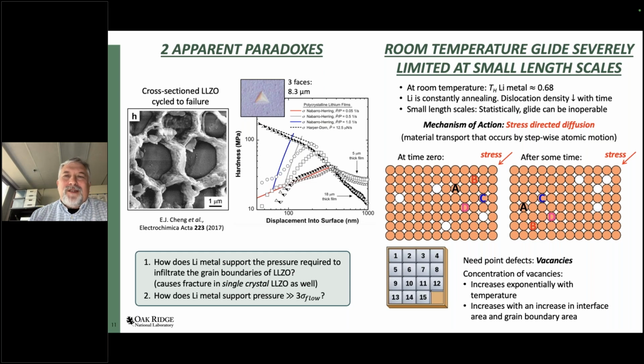Conceptually, this mechanism, stress-directed diffusion, just works like this kid's game here that allows you to move the numbers around and put them in order using the empty hole. In the case of lithium, it's going to use the vacancies in the lattice in order to transport matter away from the stressed volume of lithium. That mechanism can work quite well, but in general, it's nowhere near as efficient as glide.